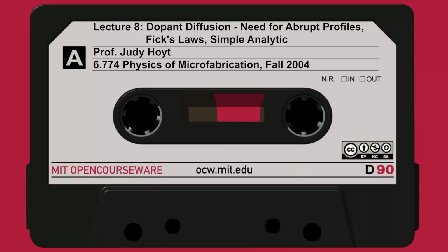So it's 1 over the integral of the carrier concentration N minus the background dopant concentration NB, so that's just the net dopant concentration, times the mobility, which is generally a function of the dopant concentration, dx.